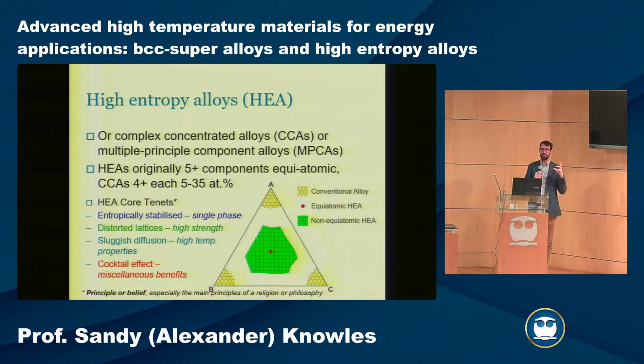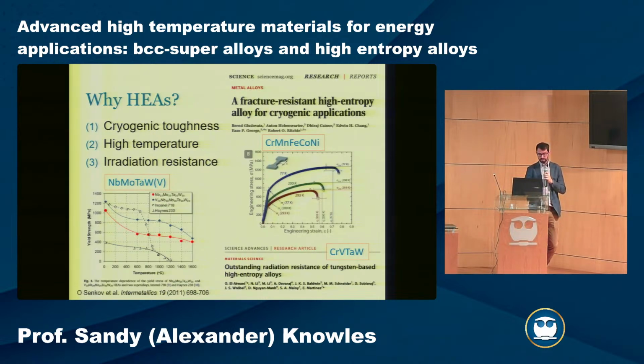We have a large number of elements mixed together, so you get a huge amount of solid solution strengthening, giving potentially high strength. It's been observed that you also see quite sluggish diffusion within the material, and you also get some cocktail effects, so there are interesting things, particularly in terms of irradiation resistance. So why high entropy alloys? They're potentially a curiosity. The particular interest is that they have some observed properties that we haven't seen in any material we knew previously. For example, and Amy will give this in much more detail later on, the cryogenic toughness.